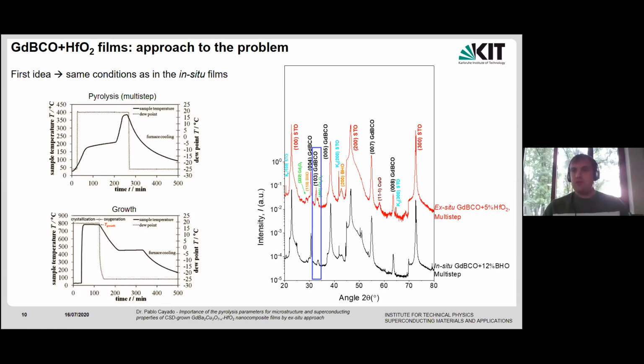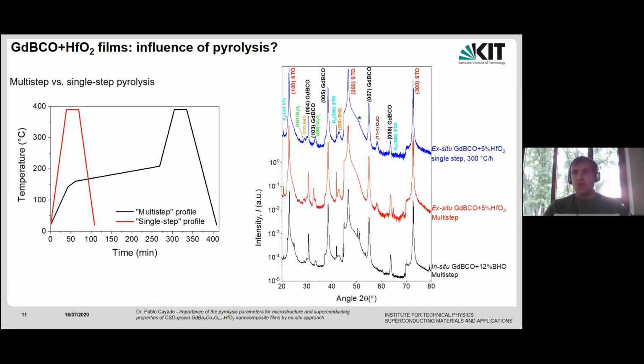When we observe that, the first idea is, okay, we have to modify the growth process a little bit: change temperature, change oxygen partial pressure, change water pressure, etc. We did a lot of experiments and we always observed the presence of 103, so we could not change or modify this presence of misoriented grains. So then we thought about the last option, which is that maybe it is the pyrolysis that is doing something, creating an effect on these misoriented grains.